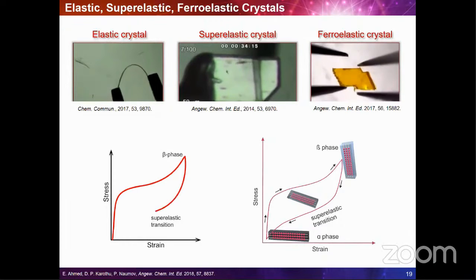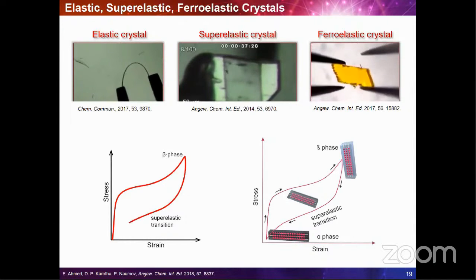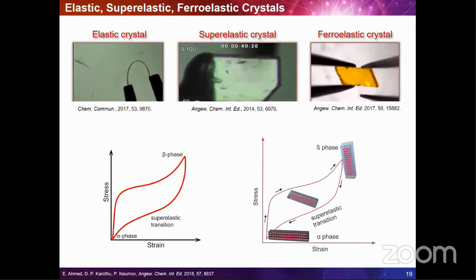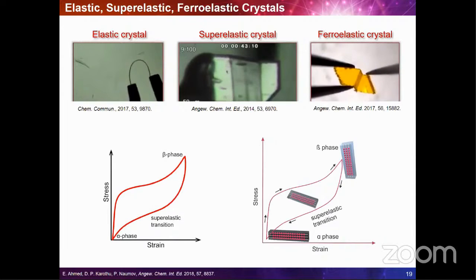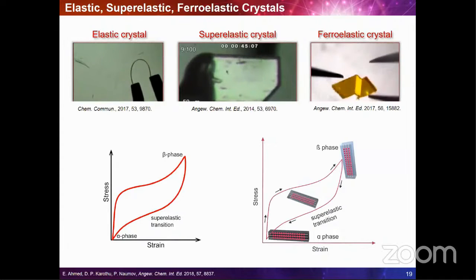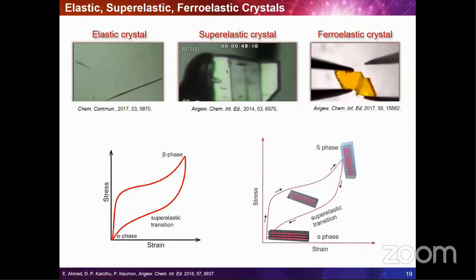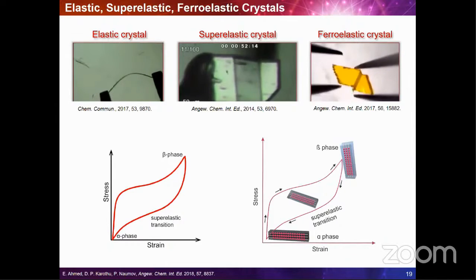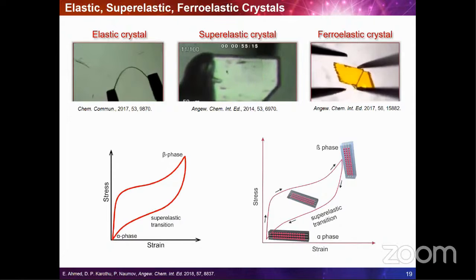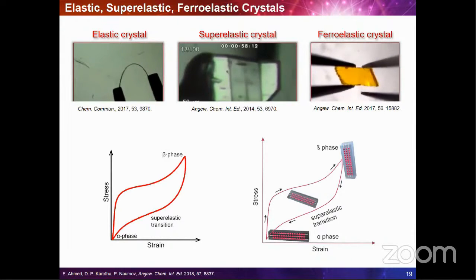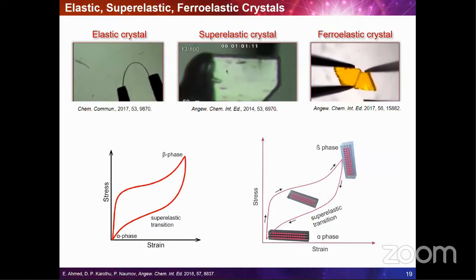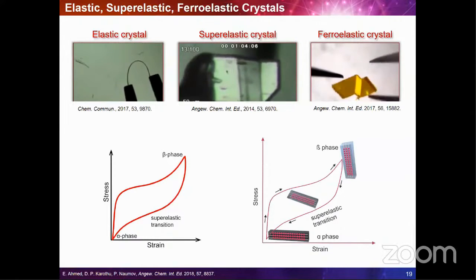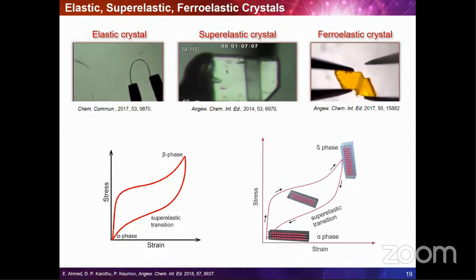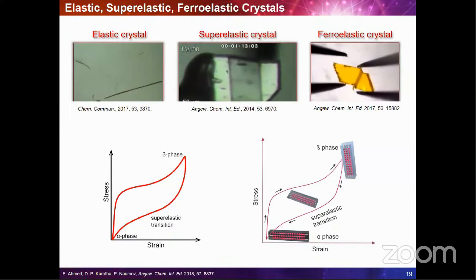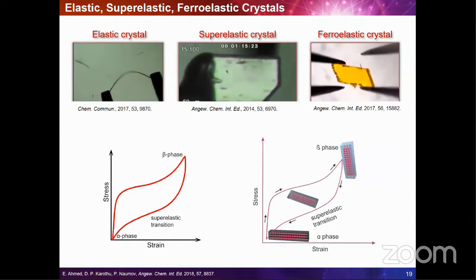Now, there are recently reported superelastic materials, superelastic crystals, which, when subjected to external stress, undergo a reversible phase transition without losing elastic energy. It is similar to the well-known shape memory alloys or the transition between austenite and martensite phases in steel. These kinds of crystals can sustain strains of up to about 10 to 12%, and moderately deformed superelastic molecular crystals are able to recover their shape by undergoing martensitic or diffusionless transformation. This property, superelasticity, can be attained either by phase transition or by twinning.